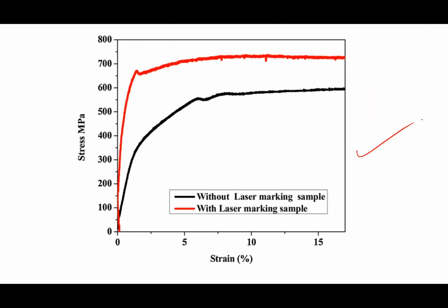It can be seen that the laser marked samples have a higher strength due to the grain refinement, lower porosity, and Ni-rich phase formation. So the results from the compression test are in line with the results obtained from the metallurgical characterization.